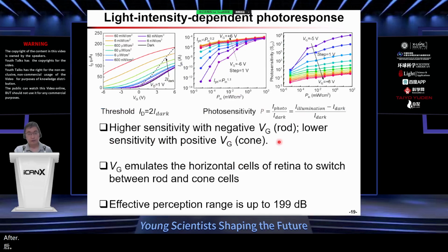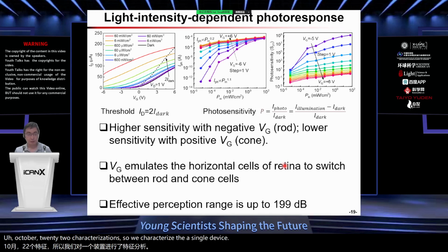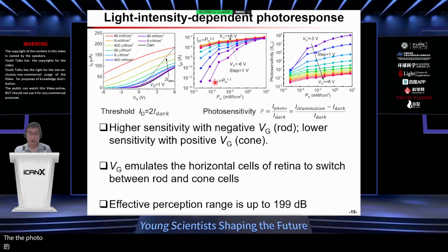After we fabricated the phototransistor array, we did the optical and electronic characterizations. So we characterized the single device at different light intensities with different gate voltages. Here you can see that with the increase of light intensity, the photocurrent actually shows sublinear response characteristics.